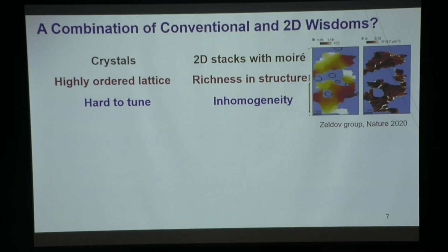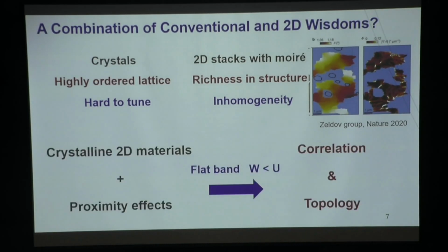And that's what you measure at a microscopic scale. So I was enlightened by the advantages of these two wisdoms, and I'm aware of their disadvantages. So what I want to do is to combine them. I want to find some two-dimensional material in crystalline form that already has a flat band and some correlation effect. And then I'm going to introduce other layers at proximity, so I can dress the flat band in my 2D crystal with proximity effects, for example spin-orbit coupling, or Moiré as a proximity effect, to make things even more interesting. And hopefully, I can find a good combination of these two wisdoms to get highly tunable and interesting correlation and topological effects. The question is, what kind of 2D crystal am I going to use as my building block?